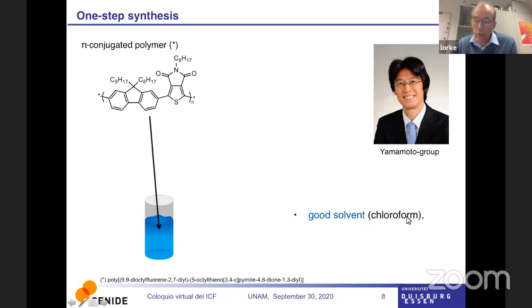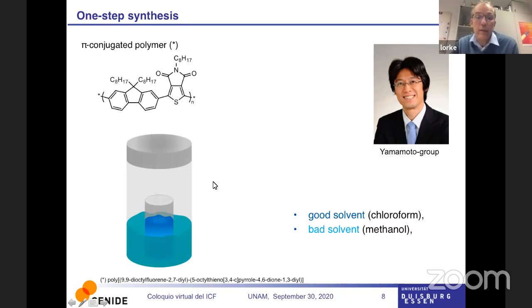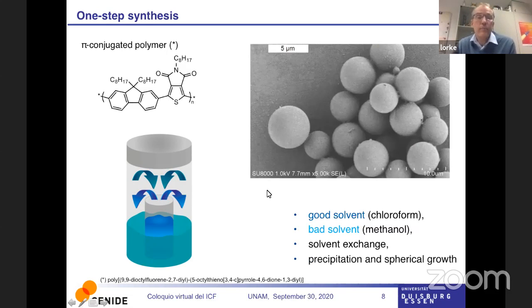So you get this polymer, maybe from friends who synthesize this, and you put it in a good solvent. In this case, it was chloroform. And then you put the entire beaker into another beaker and close the whole thing up. And the other beaker is filled with a bad solvent, in that case, methanol. And then you have something that's called solvent exchange, because the vapor of these two solvents will mix and then exchange with their origin. And this way, the inner solvent will become worse and worse. And after a while, the polymer will precipitate.